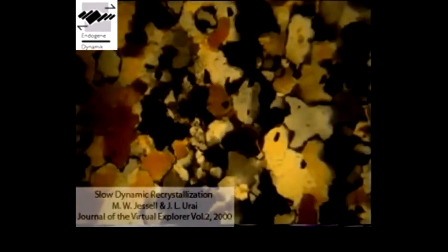So we can start to see new grains forming and growing at the boundaries and interstices of these prior grains. There's a couple here that have been growing as we're deforming the material. The orientation of those new grains is typically very different to the parent grain. It's actually a condition that those orientations are different for them to grow. Otherwise, they just stay there as a single broken down grain within the grain structure.